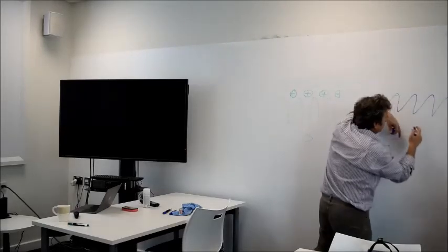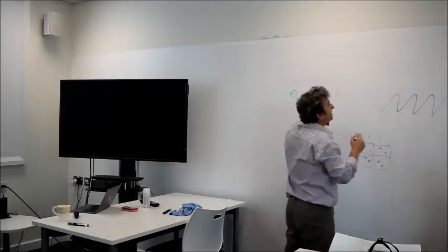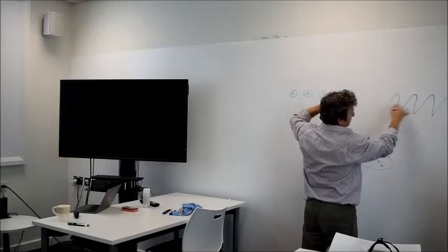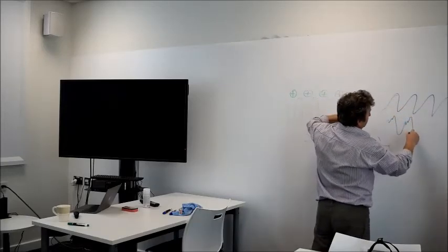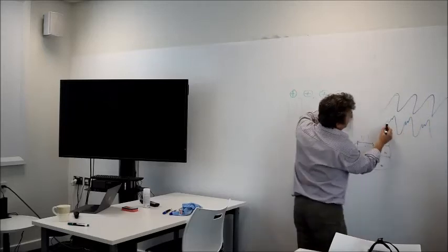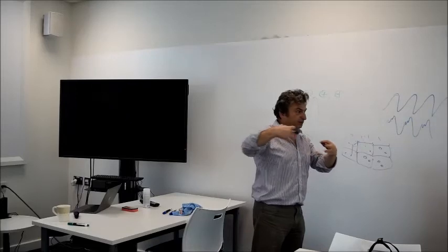You understand, and goes down. So you have kind of a sawtooth structure like this. But what they discovered, the sawtooth structure is not as simple as this one. It has some little wiggles here. And if you measure each of these wiggles, this is exactly the dimer-dimer distance along the row.